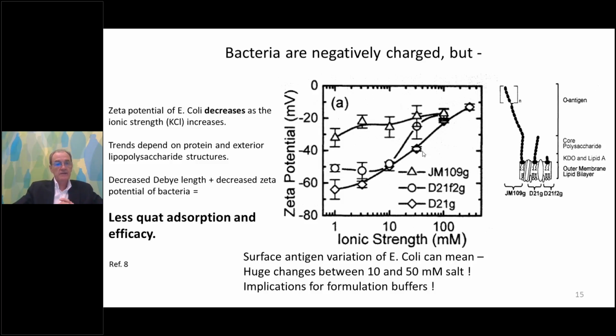But speaking of electrolytes, the charge on the bacteria matters as well. And so here we see a couple of different E. coli bugs that express different lipopolysaccharides on their surface, and their charge can vary amongst different strains of E. coli. And worse yet, the zeta potential, a measure of the charge on the bacterium, for one of those bugs changes a lot, between 10 and 50 millimolar electrolyte concentration. So that's a very large shift in the charge of the bug. And that means, again, the potential for a reduction in the quat adsorption and efficacy just by our changing the nature of the electrolyte package in our wipes lotion. So we have to mind not only the electrolyte level and co-surfactant we're using, but we also have to think about the variation between the various bugs that we're trying to attack.